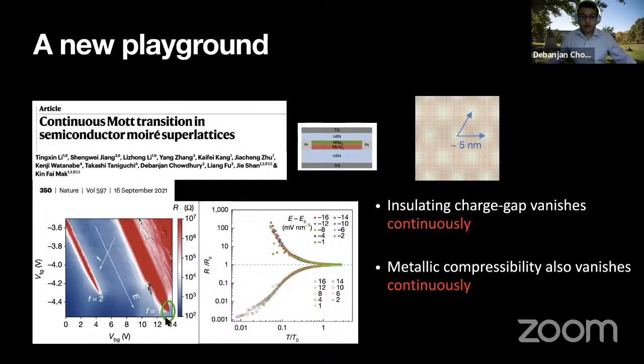Now, this is of course very hard to do in any solid state material, but that's the amazing tunability associated with these systems. And so you can immediately see that you go from a very resistive state, which is an insulator, to something that's like a metal. And in fact, if you look at the transport data and do the usual kind of scaling collapse, this is what it looks like. So all of these curves, these correspond to the insulator, and all of these curves, they are the metal, okay? Moreover, just by fitting an activated form to the resistance here on the insulating side, you can extract a charge gap, and indeed it vanishes continuously across the critical point.